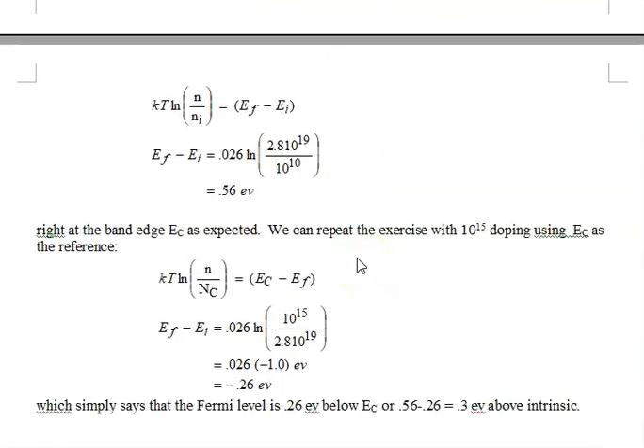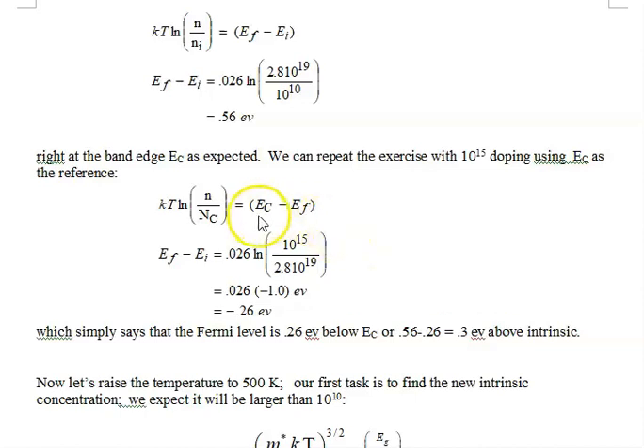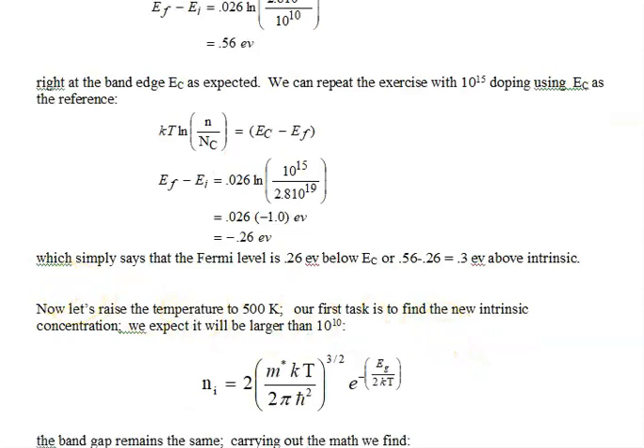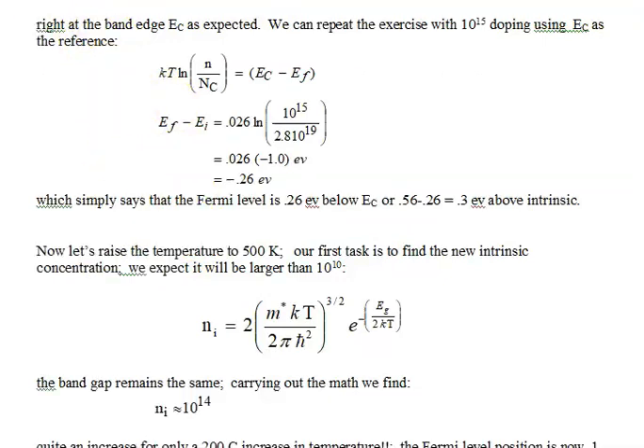So let's put that in someplace. Right here. N is 10 to the 15th. N sub c is 2.8 times 10 to the 19th. So we find it is negative, exactly as we would expect, 0.26. If it's 0.26 below E sub c, it is 0.3 above E sub i. Okay, so now let's look at the effect of temperature. Before we start the temperature, let me do a sanity check. I said it's 0.26 eV below E sub c, which means it's 0.3 eV above, not E sub c, but intrinsic. And of course that all makes sense. 0.3 plus 0.26 is 0.56.